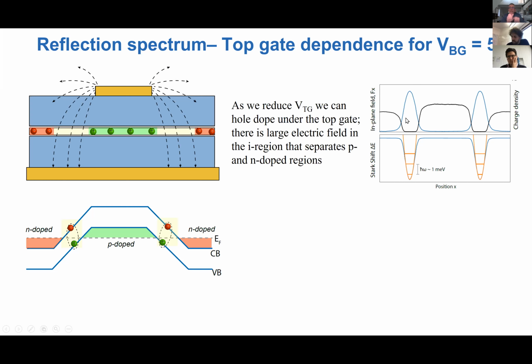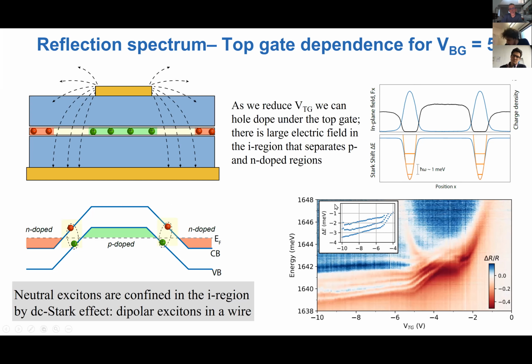What that means is that these large fields create a large DC Stark effect and redshift the exciton energy such that one can have a trap for excitons precisely in this relatively narrow, on the order of 10 nanometer, undoped region separating the electron and hole doped regions. Okay, and this is precisely what we see. So if we start out with the top gate at 0 volts, we don't see anything because this is basically electron doped. There is no resonance here.